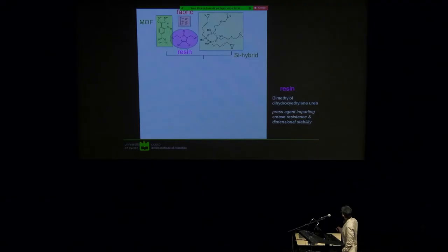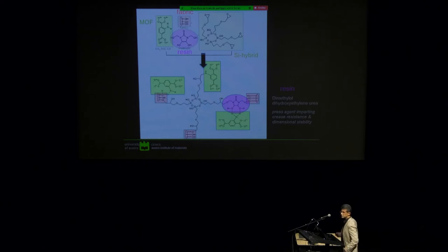And so, what we did is, as a glue to attach the crystals to the fabric, we used a hybrid material, a silicon-bearing hybrid material. And of course, the MOF material is this, the linker is this one, and it can be derivatized with NH2. Normally, the fabrics also have resin, which imparts some resistance and mechanical properties. And of course, you have the fabrics with the OH groups. And with this epoxy ring, of course, you can react with all these functionalities. And then also there are hydrogen bridges that can be built and so on. In other words, this glue works very well and keeps the crystals attached to the surface, to put it in a very simple way.